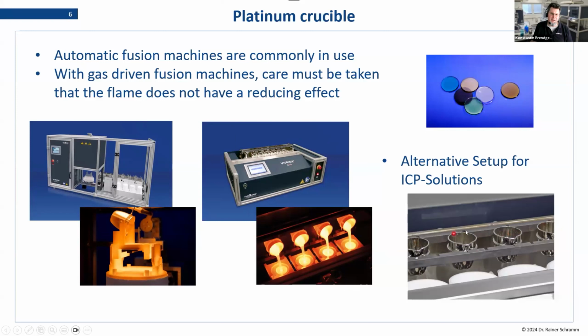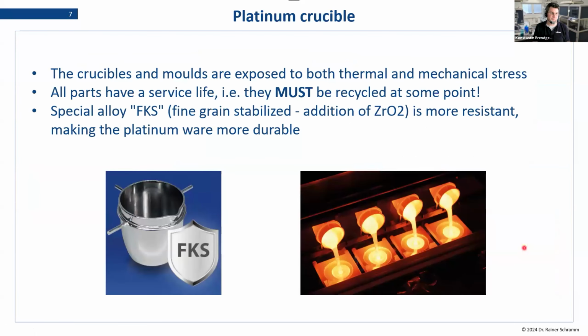There is an alternative setup to do ICP solutions. In that case, we only use the crucibles in platinum. The target here is a Teflon beaker with an acid. So we basically pour the liquid fusion into the acid to dissolve it and form a liquid for ICP. Real quick, we use the same crucibles here.